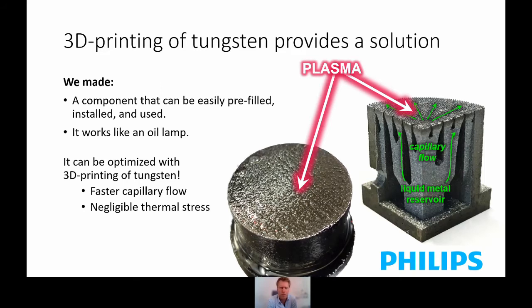So 3D printed tungsten is not as strong as regularly manufactured tungsten. It has only about half the strength, let's say, but it's absolutely irrelevant because the stresses are also irrelevant. And from that perspective, for those of you who are familiar with the neutron loading, neutrons continuously degrade the materials in fusion reactors. That's a big problem. But we might wonder, is that still a problem here? If the material has virtually no need for strength, does it matter if we lose a little? So that is actually a very interesting side note here.